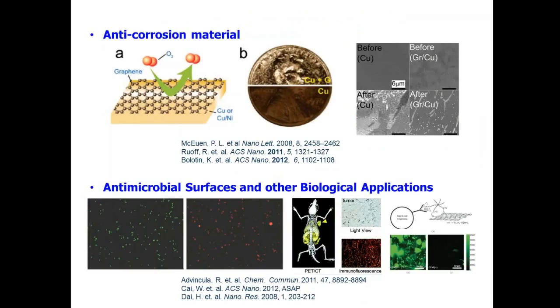For example, as a barrier material, a one-layer graphene coating on a copper-based metal coin can actually be enough to mitigate corrosion. That is, a very, very thin film of graphene nanosheets overlaying copper is enough to prevent the material underneath the graphene from being oxidized.